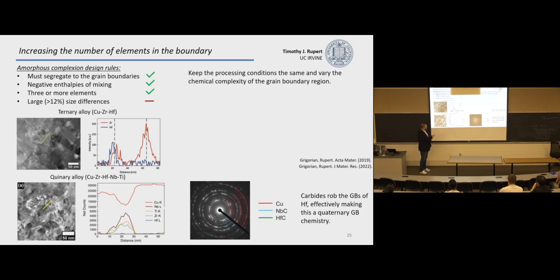Now this, you've probably seen things like this with things like high entropy alloys, where people are mixing things in. I do want to sort of clarify, this is not really that. This is something where we have 92% copper, 2% of the other things. So it's still primarily copper. The reason I'm showing this data is only that, in the copper, zirconium, hafnium, you get grain boundary segregation of the two. Even though I added in 4 doping elements here, it's important to double check yourself.